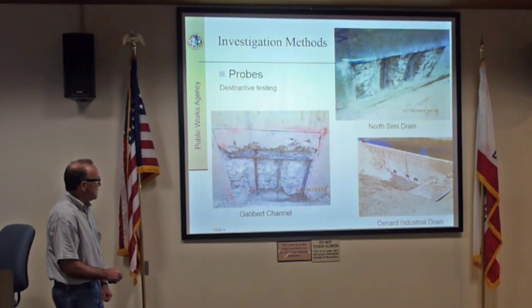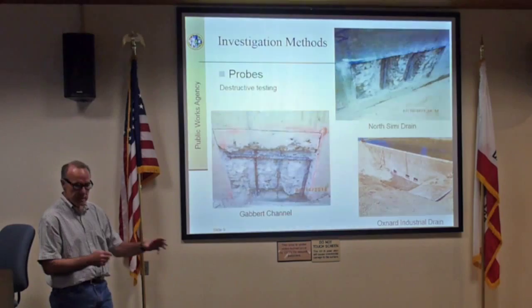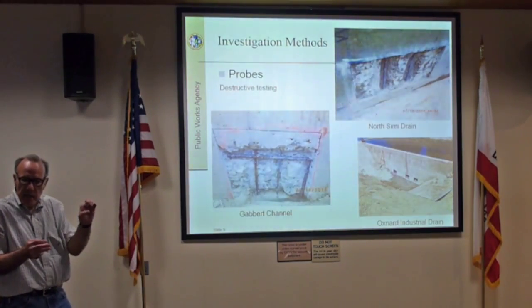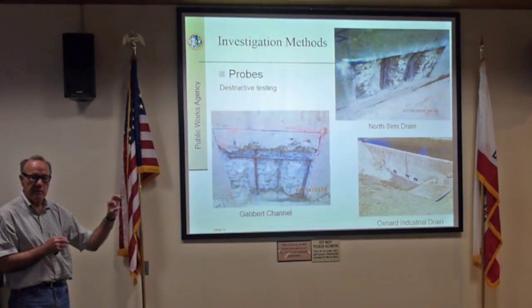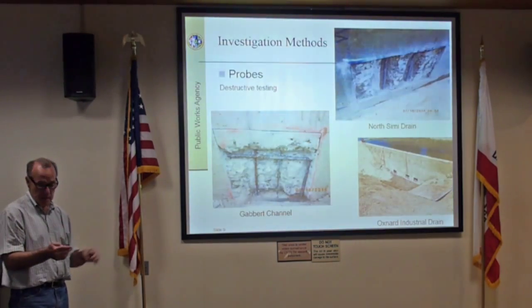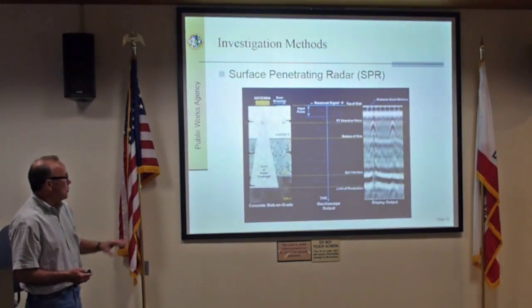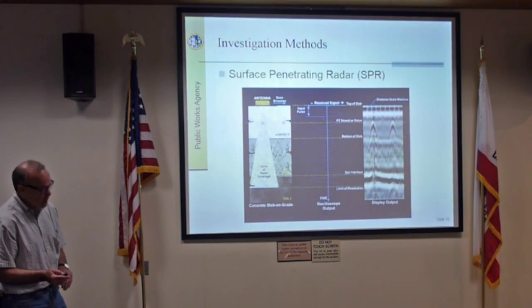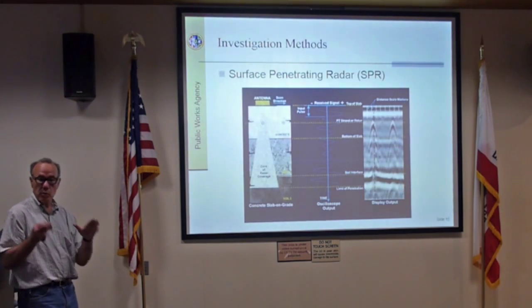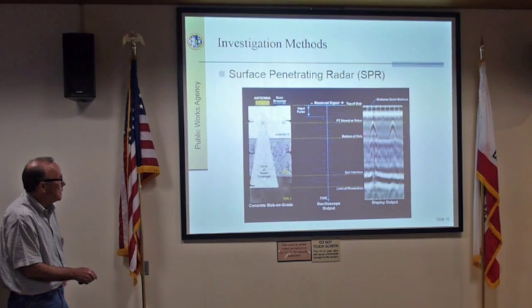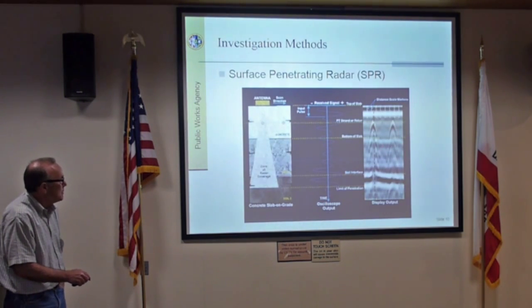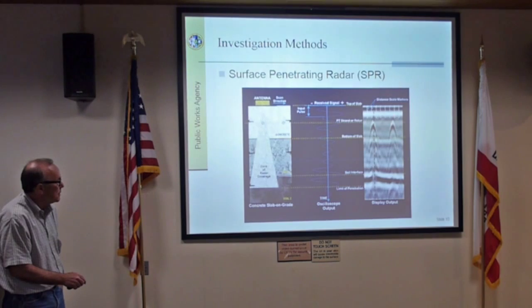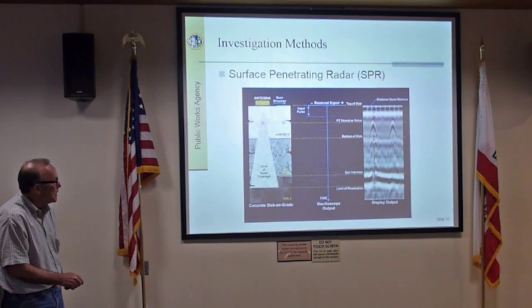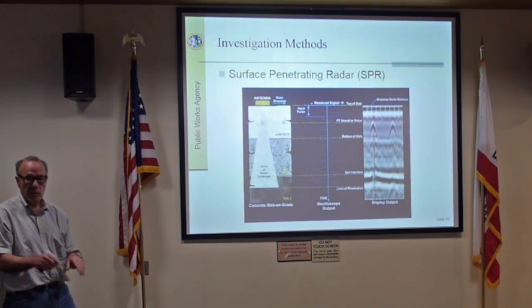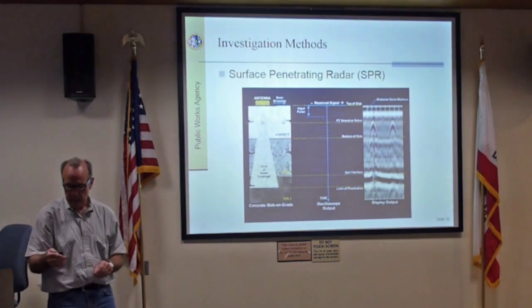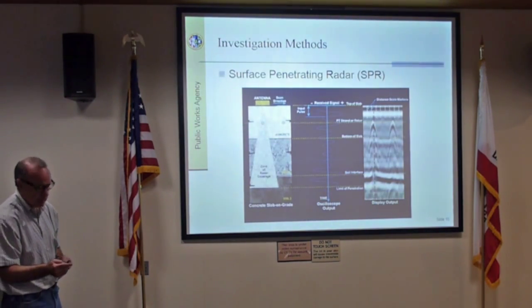And this is the type of corrosion that makes it more difficult. It's both macrocell and microcell. You can have very, very small areas that are corroding very, very fast, but they're very difficult to detect. All radar does is give you an idea of where reinforcing steel is, so we know where to go out when we do our probes. With the radar signal, you can see these little hyperbolic signals, and it gives you an image. That's really the reinforcing steel, so we know how to capture the area of interest.